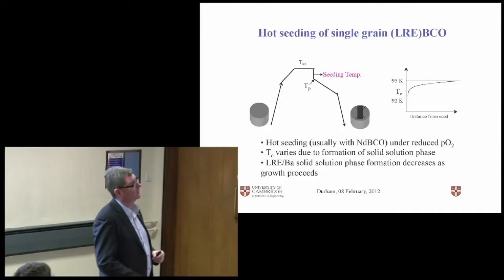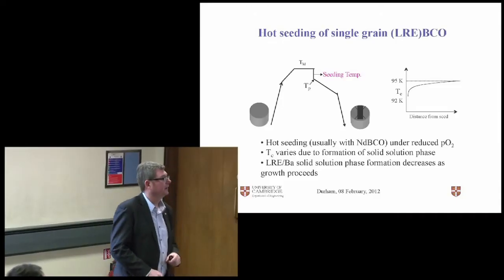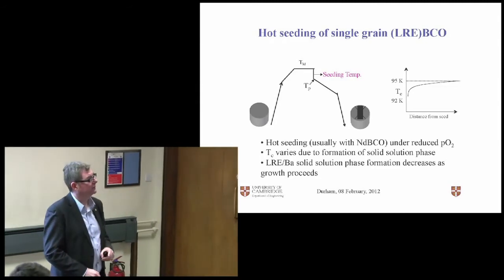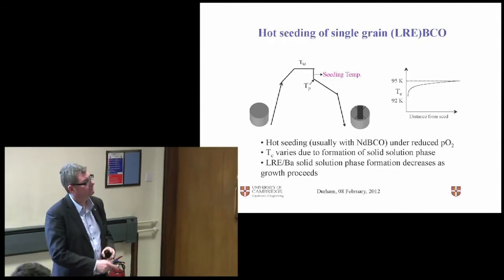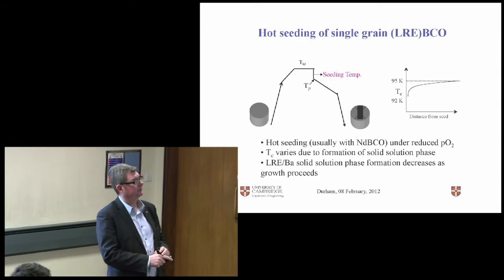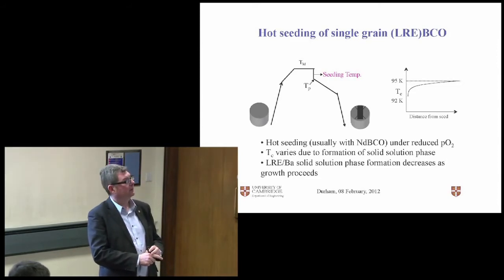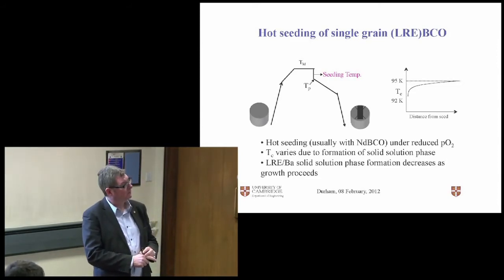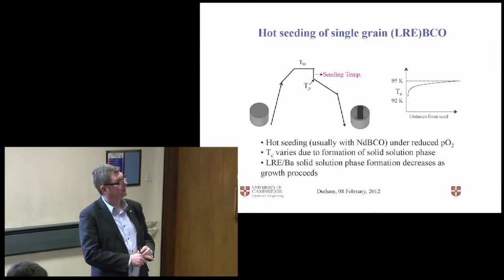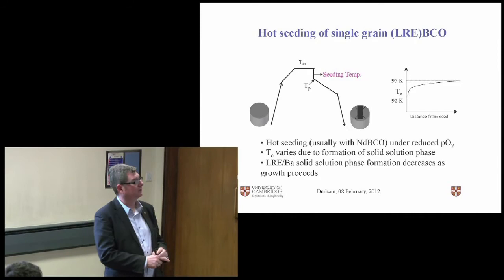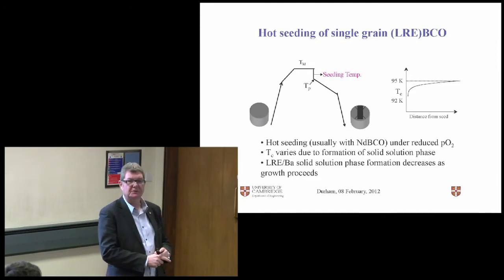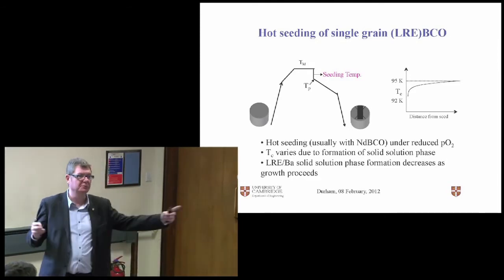So the Japanese use a hot seeding technique, and I've seen the lab where this happens. It's pretty spectacular, I have to say. You take your material, heat it up to the decomposition temperature, allow it to peritectically decompose, cool it quickly to just above the peritectic temperature, open the furnace door, and put your seed on the sample. The one I saw was a tube furnace.